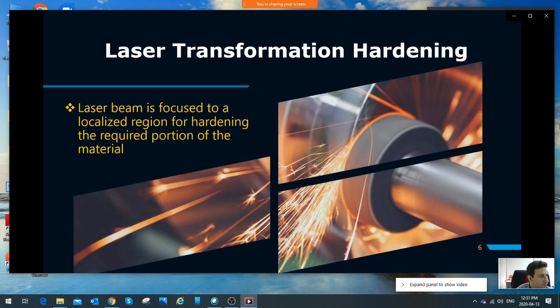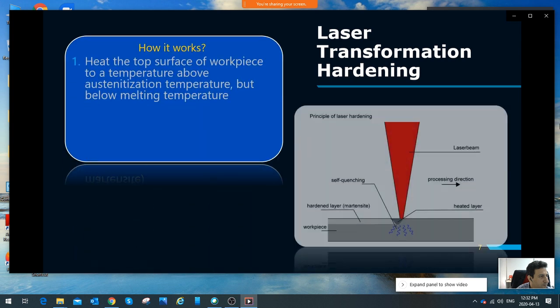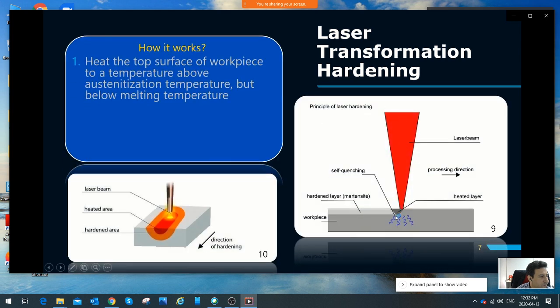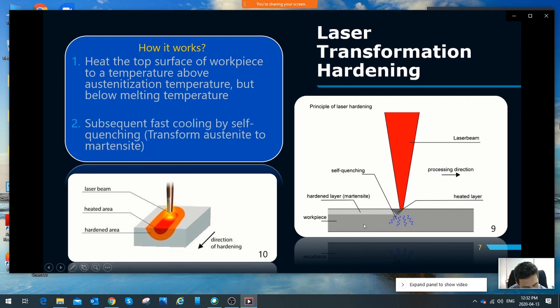In laser transformation hardening, the laser beam is focused on a localized region for hardening the required portions of a material. And how does laser transformation hardening work? At first, the laser beam heats the top surface of the workpiece to a temperature above the austenitization temperature but below the melting temperature. And due to the rapid heating that results in rapid cooling, there is a phase transformation from austenite to martensite. Here, as you can see, there is self-quenching and the layer is hardened into a martensite layer.